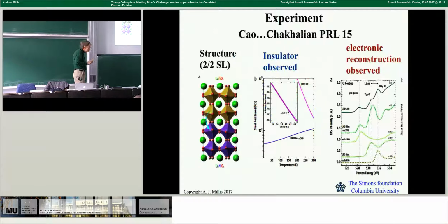Right? So a year or so after Hanghui did that, the group of Jak Chakhalian fabricated this structure. That's this picture. So they were able to grow essentially this. They observed it to be an insulator. This is when they grow under the same circumstances, just a film of lanthanum nickel oxide only. They get a metal. When they grow the superlattice, this is the same electrical resistance. They see an insulator, resistance increasing very rapidly as you lower the temperature.